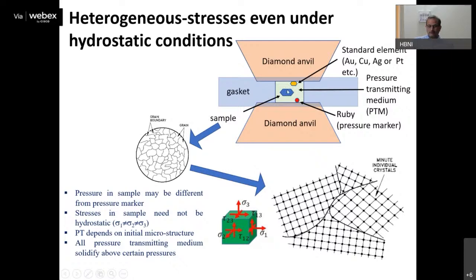So even when you are applying pressure on this sample, meaning all the normal components are equal, if you try to describe the stress states within the sample, they may not be completely hydrostatic. Because here your grains are touching other grains. There are interfaces. So here the stress state will be quite different from the stress state here, or the stress state at the boundary of the sample. So even in hydrostatic conditions, there is a possibility of heterogeneous stresses in the sample.